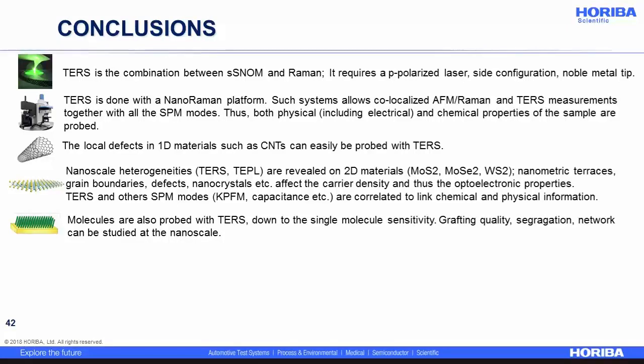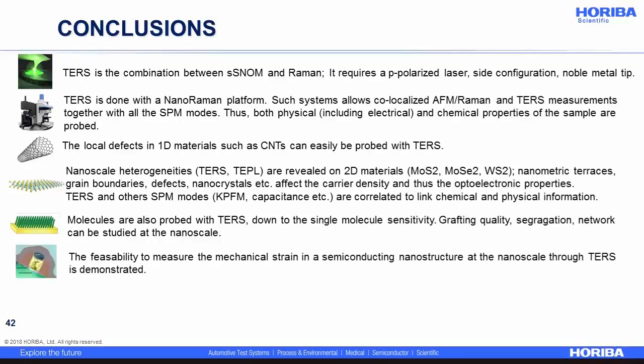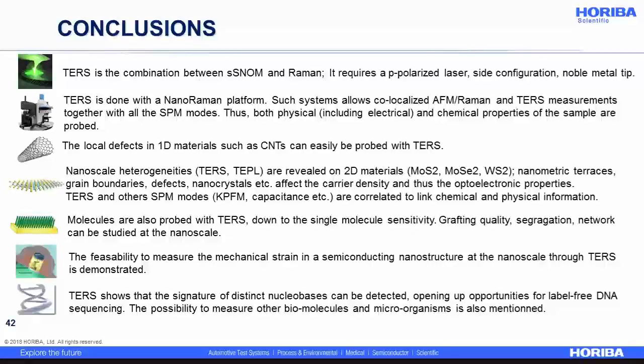The grafting quality, the segregation, the network can be studied at the nanoscale. The feasibility of measuring the mechanical strain in a semiconducting nanostructure at the nanoscale through TERS has been demonstrated. And finally, TERS shows that the signature of distinct nucleobases can be detected, opening up opportunities for label-free DNA sequencing. The possibility to measure other biomolecules and microorganisms is also mentioned.